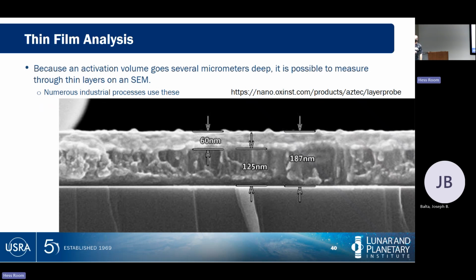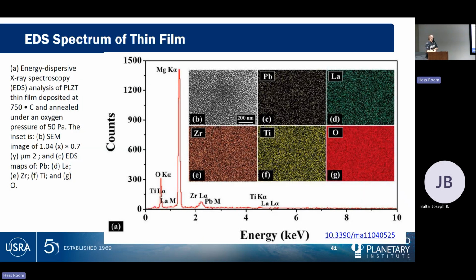Same thing with the backscatter image. If I had 5 different layers next to each other, the backscatter contrast will be a function of the thickness of a layer. So here is an EDS spectra of a thin film deposited at 750 C and annealed under an oxygen pressure. I don't know exactly why on earth they were doing this. This is material science applications, but they are material science applications of an SEM.